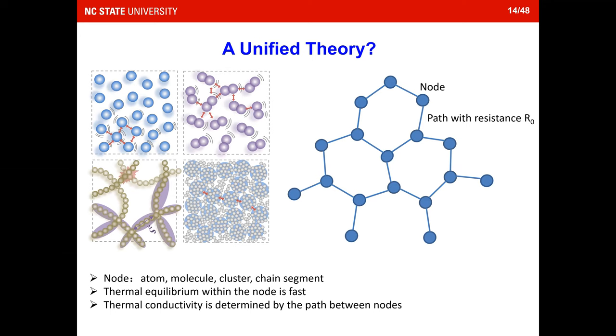If you think about this as a network, and each of the nodes represents either a single atom or molecules or clusters or chain segments, can you actually unite them in a network? And then figure out the path with a resistance between the nodes, which probably can help you explain the thermal transport, right? Because we know that within a node, the thermal equilibrium will be very fast. And between the nodes, the thermal transport will be slower, and that determines the thermal conductivity.